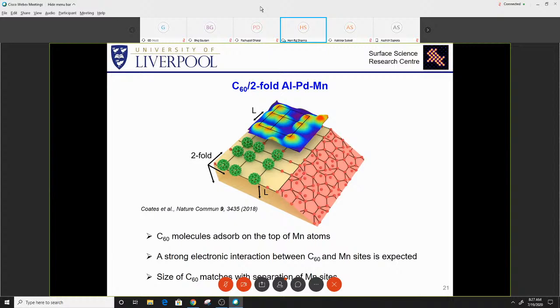So your C60 will simply go and form a pentagonal structure, which I just showed. But if you do the C60 on the 2-fold surface, then C60 will go on the manganese side of the new structure we call Fibonacci square tiling. This is the mathematical tiling predicted some time ago, but nobody really detected the 4-fold scenario.